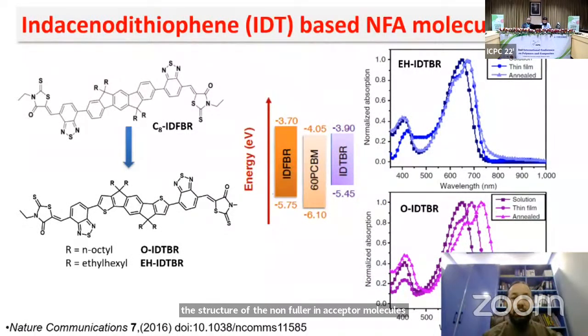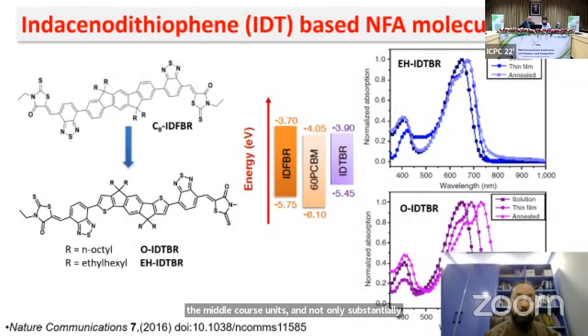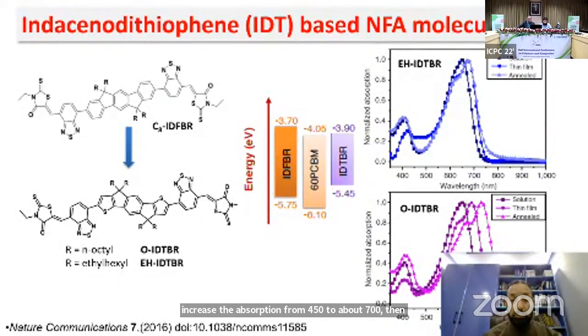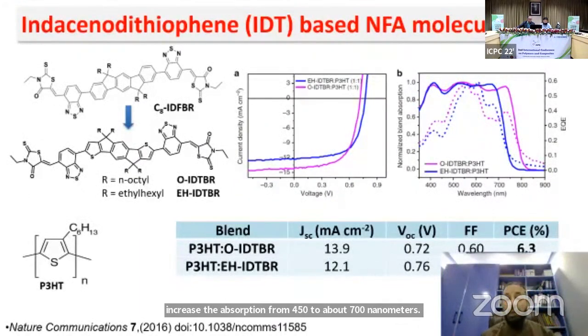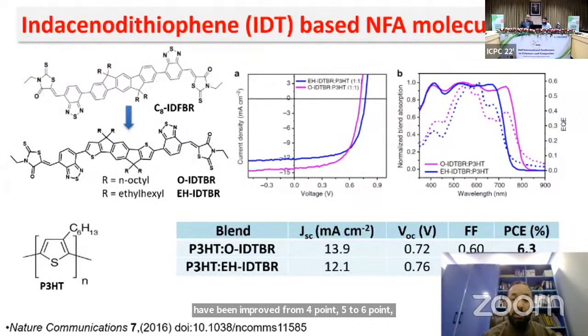What we did is change the middle core from indenofluorene to indacenodithiophene. By putting two thiophenes on the periphery of the middle core unit, we substantially increased the absorption from 450 to about 700 nanometers, and this gave us a very substantial improvement in solar cell performance as well. The power conversion efficiency improved from 4.5 to 6.3%, which was one of the best solar cell results reported with poly-3-hexylthiophene.